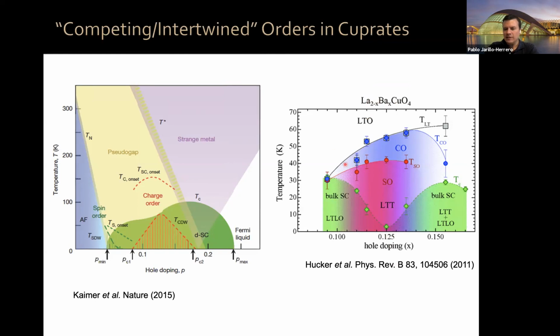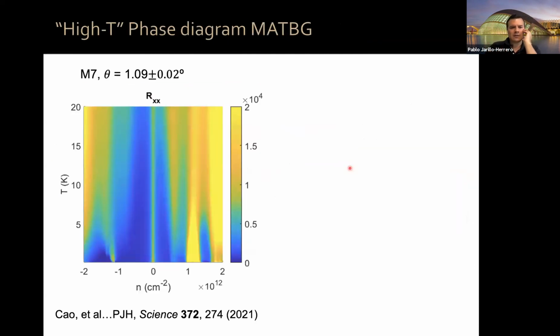So this is something that has been investigated a lot in the cuprates, and other materials also exhibit this type of competing phases between superconductivity and something else. Now let's look right away at data in magic angle twisted bilayer graphene. This is a high temperature, high temperature in quotes, but let's say up to 20 Kelvin, much higher temperatures than what I was showing yesterday, for a device 1.09 plus or minus 0.02 degrees.